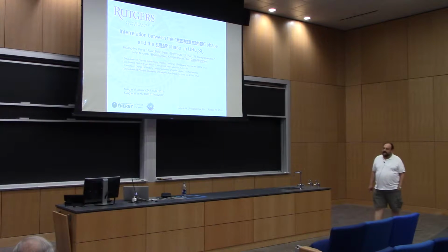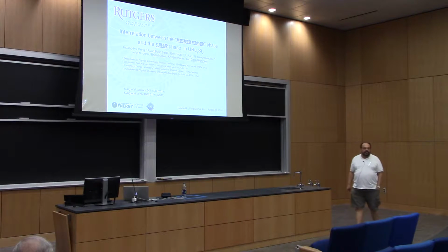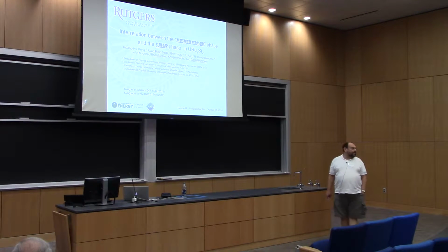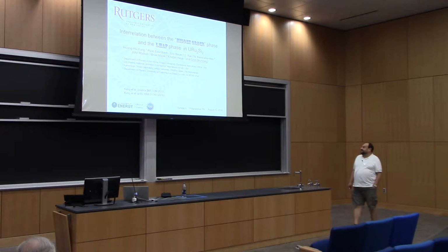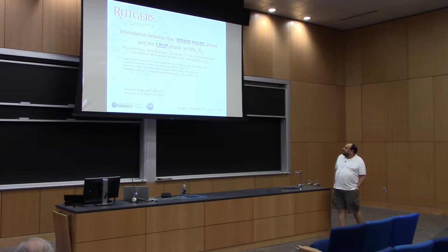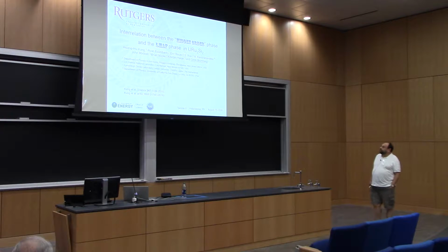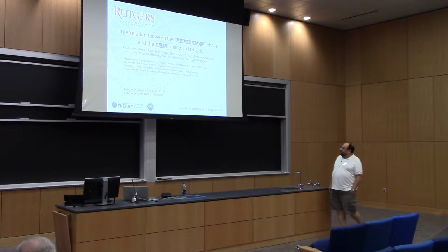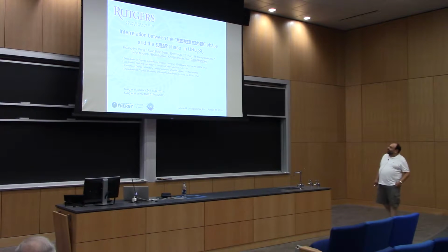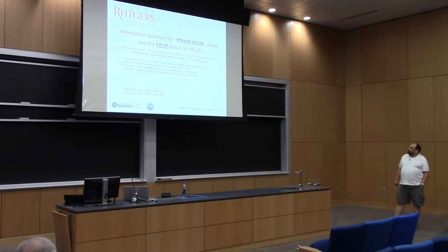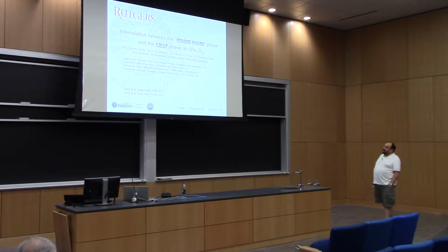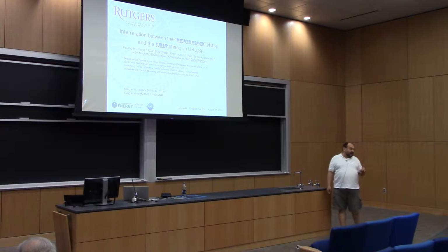I said that if we see a characteristic electronic mode, we can apply good theoretical analysis. I didn't know that such a mode exists, and we were very lucky. Sean presented the results in previous talks. Sean actually insisted that there is a mode there. I didn't believe it initially. He pushed the spectroscopy down to 2 wave numbers to show that at very low frequencies there is a very nice strong collective mode. The mode is exactly the same as has been seen by neutrons, and then we could apply the analysis.